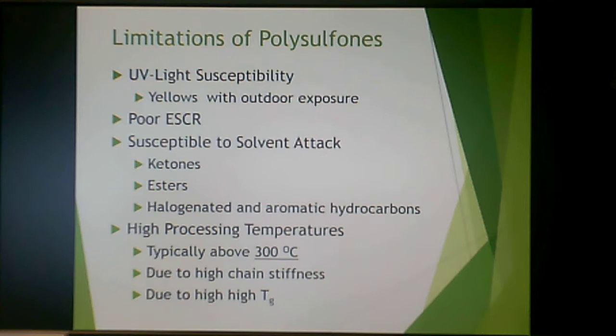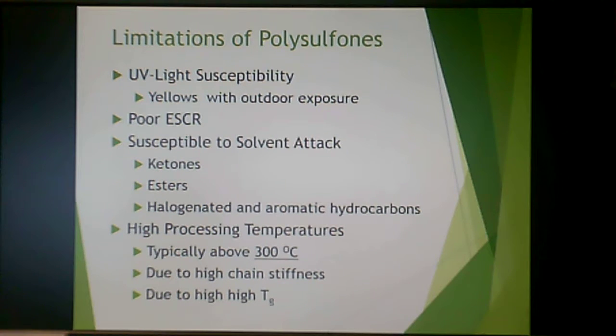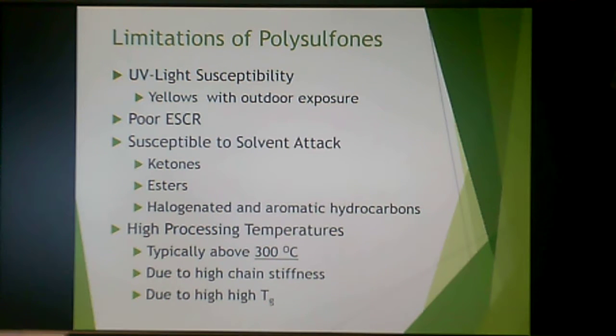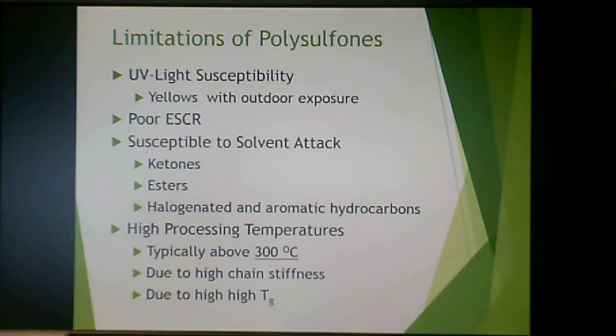Polysulfone does yellow with outdoor exposure, so it does not have very good UV resistance. It also has poor environmental stress cracking resistance — that's where polyphenylene sulfide has an advantage over polysulfone. It is susceptible to solvent attack, especially halogenated and aromatic hydrocarbons, and it has a high processing temperature. Because of its high Tg, you have to get it pretty hot to achieve flow, as these chains are very stiff due to the many aromatic rings in the backbone. Processing temperatures are typically above 300°C, which requires a lot of energy.